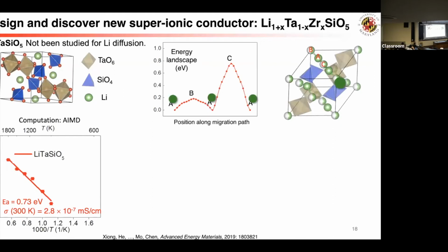What we did, as we showed in the initial case, is we find that if they have these higher energy sites that are not occupied, then we dope these materials to add lithium to the higher energy sites. And once that is added, we activate this concerted migration mechanism that I showed you before.